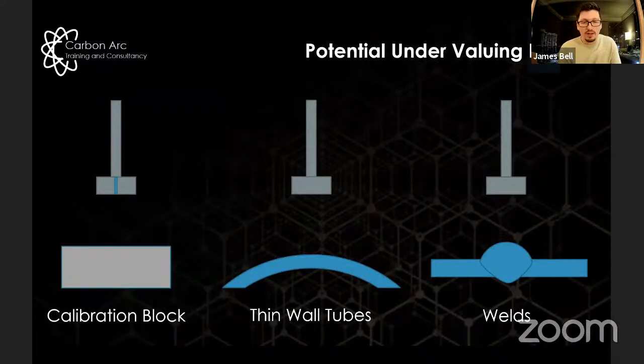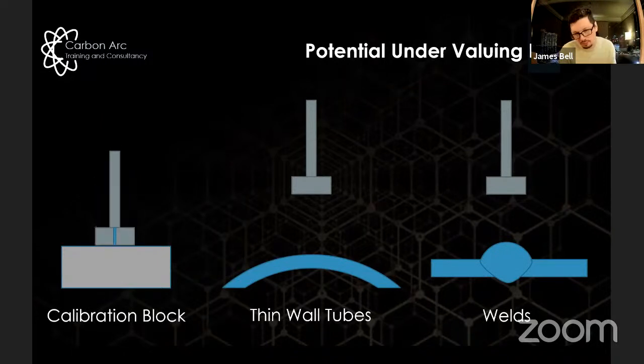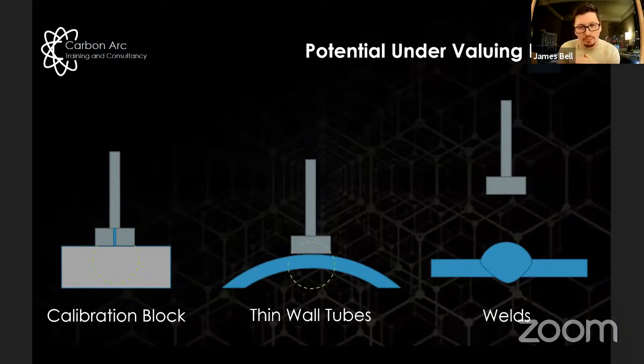So what was happening? Well, we started to get to the point where I was like, okay, how are we getting these results? So on a calibration block, you bring the probe down to the surface and it takes a magnetic reading and you get a result. That works. That was proven fairly consistent. But when we do it on a thin wall tube, we bring the probe down. In our area of test, a lot of the time is empty. There's not a lot of material in it.